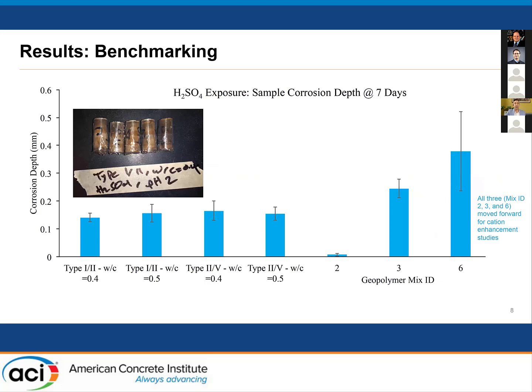And so what I'm showing here is the one-dimensional corrosion depth measurements of cylinder samples of all of the formulations that we tested, including our 4 ordinary Portland cement paste controls in comparison to our geopolymer cements. These samples were exposed on one surface only, one face of the cylinder, in a pH 2 sulfuric acid solution for 7 days, just to get a relative comparison of that corrosion depth. So we were able to measure the depth of that sulfuric acid degradation on each sample after 7 days of exposure.